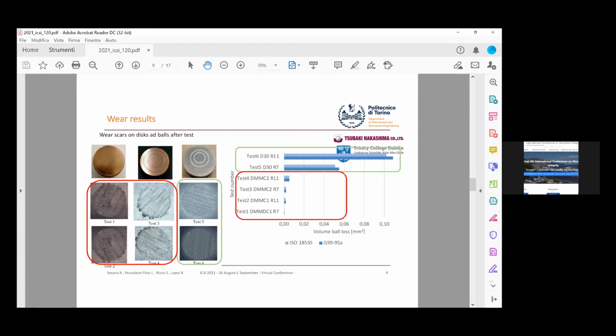These results are confirmed by profile measurement and by visual and optical microscope observation of the wear track on the disc. When considering the entire set of experimental data obtained from tests carried out with the DMMC, it can be observed that the volume loss was found to increase as the local linear speed decreases.